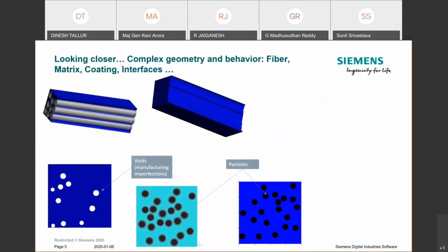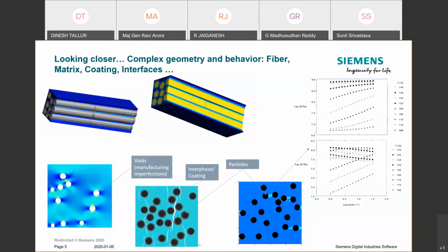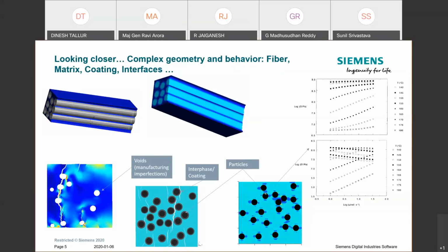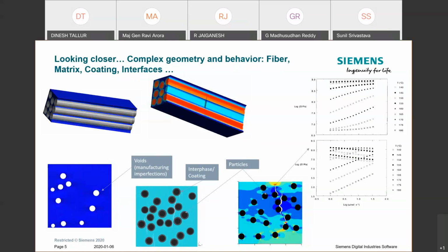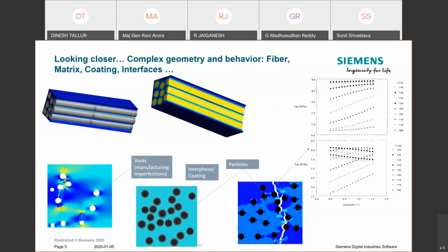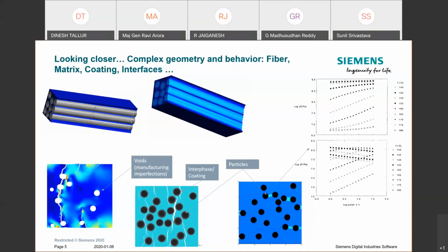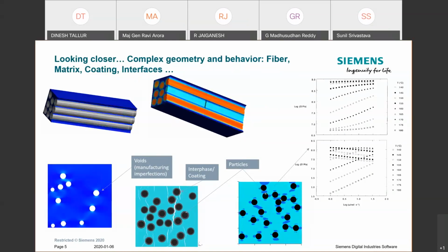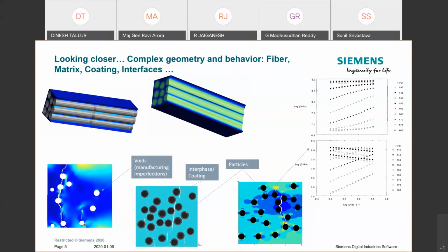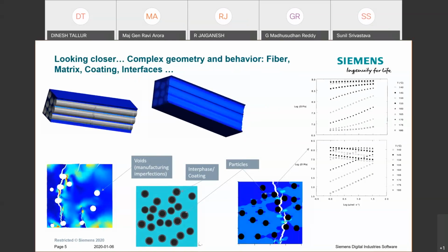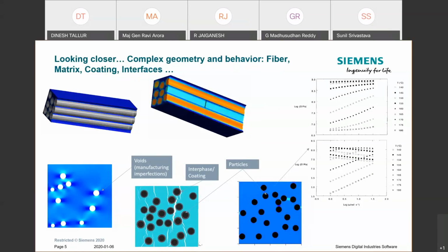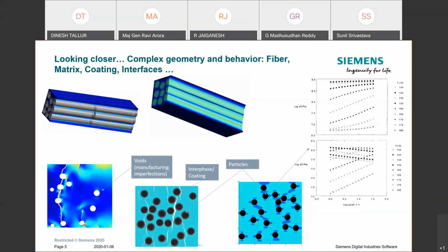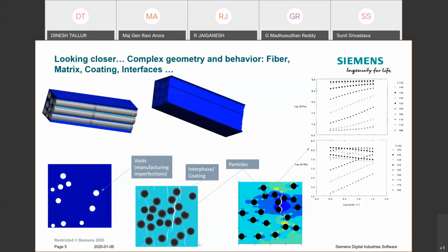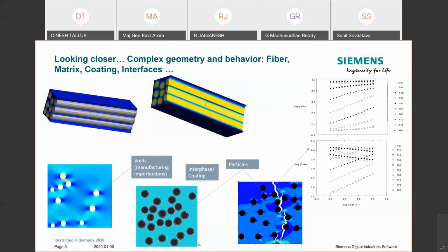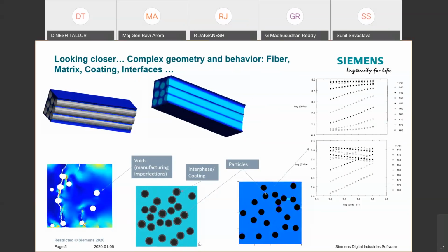Typically, when you start modeling the microstructures at a micro scale, the complexities involve voids that could be created during manufacturing, or cracks which may be initiated and propagated within the fiber, the matrix or the interfaces, or the behavior of the fibers, which could be anisotropic, highly nonlinear, and sometimes time and temperature dependent as well.